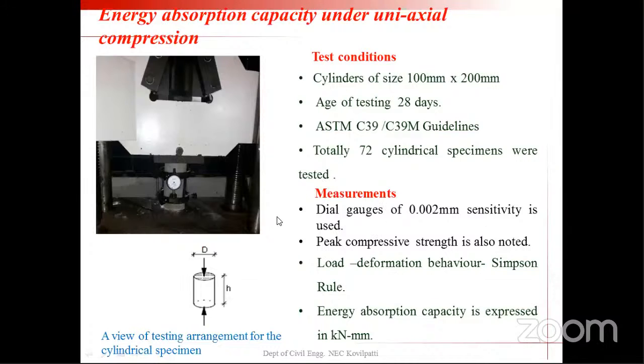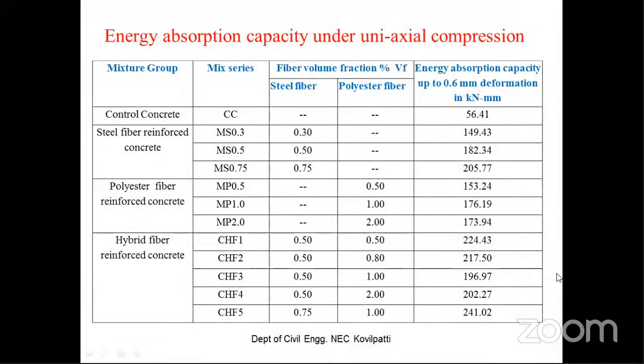So again, the dial gauge has been used, the load deformation behavior is noted and the curve is plotted. Using Simpson's rule, I found the energy absorption capacity. For comparison purpose, I have taken the energy absorption capacity up to 0.6 mm deformation. Last time I took the energy absorption capacity for split tension up to 0.4 mm. Here it is taken up to 0.6 mm.